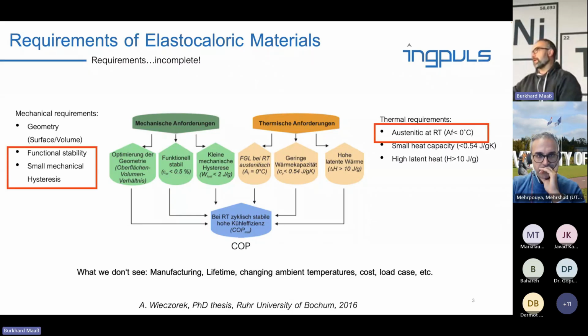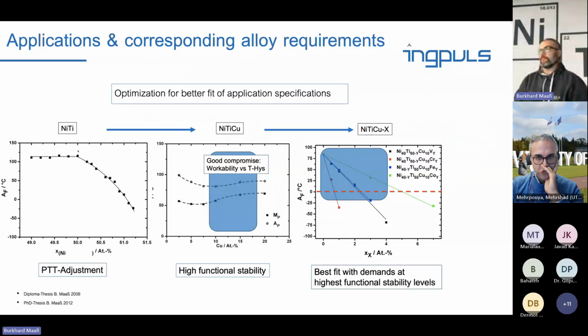So let's look at some of these points. Functional stability, small mechanical hysteresis, and austenitic at room temperature. So we as material developers look at some points and try, okay, how do we achieve this? For example, everybody knows that in NiTi, if you want to decrease your phase transformation temperatures, you can just increase the nickel content or the Ni to Ti ratio. And then if you are above 50.0 atom percent, then the phase transformation temperatures will go down.